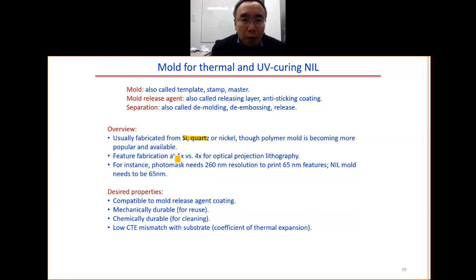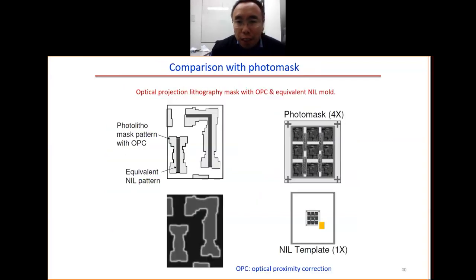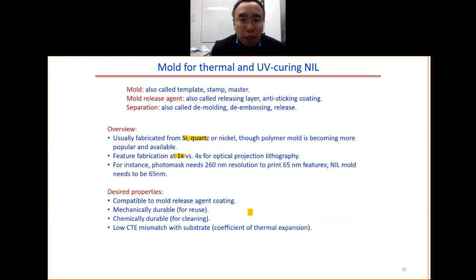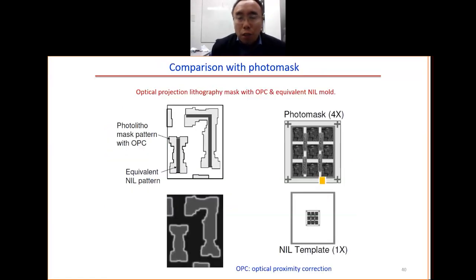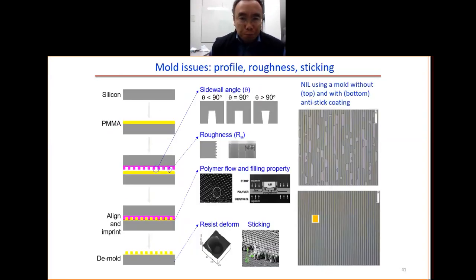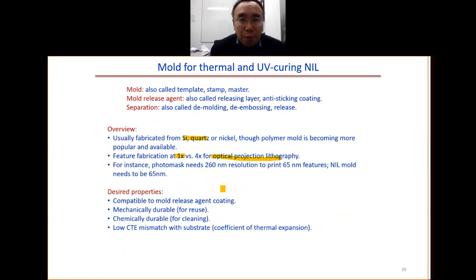For the imprint, the feature is 1 times. That means the feature size is the same as on the imprint mold. But this is different from optical lithography. For optical lithography, as we have seen before, the feature size on the photo mask is 4 times that of the final feature we want on the wafer. For example, for the case of 65 nanometer features, for optical lithography, the feature size on the mask is 260 nanometer. For the imprint, the feature size is 65 nanometer.